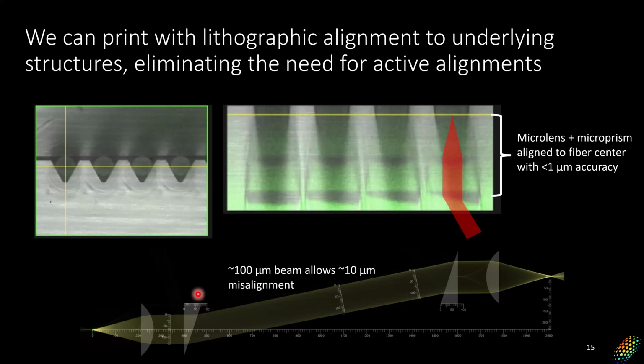Because these components are perfectly aligned here, you get this very regular expanded beam. Instead of trying to match a 10 micron mode, which is typically what you're trying to do going from fiber to fiber, where you can only withstand roughly 1 micron of misalignment between the two before you start seeing 1 dB loss, now the thing you're trying to align is a roughly 100 micron mode. So you can handle roughly 10 micron misalignment for the same loss that you would get for 1 micron in the 10 micron fiber case.